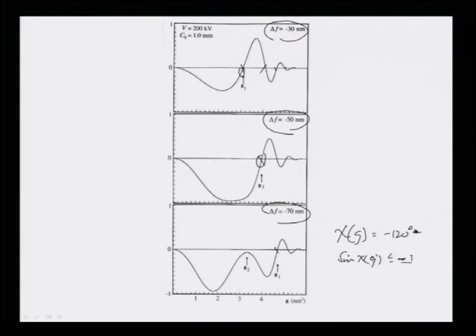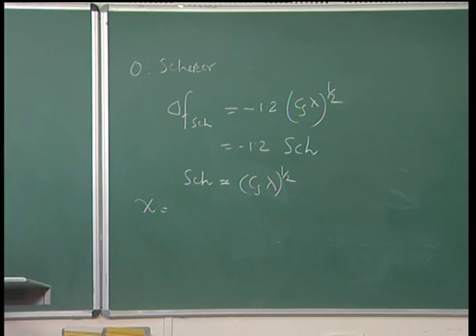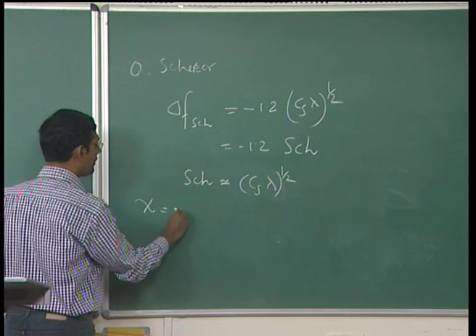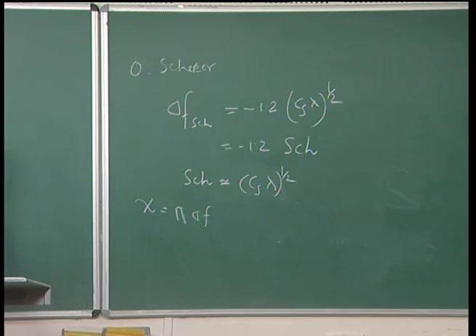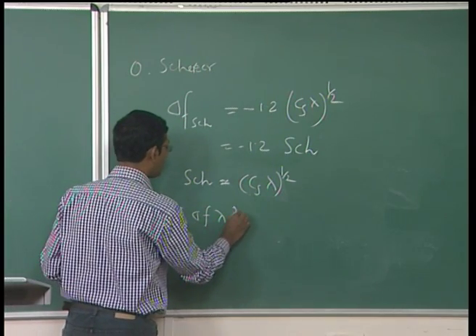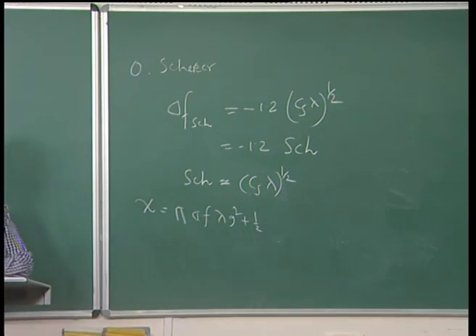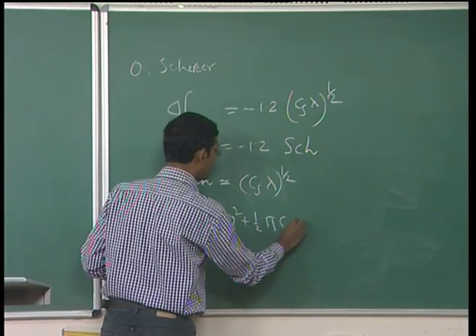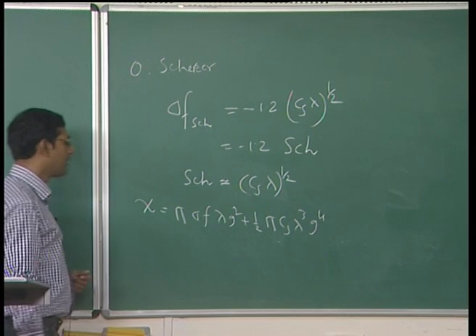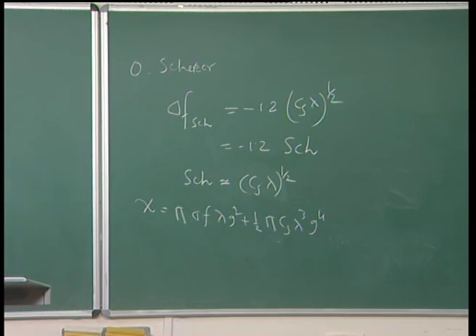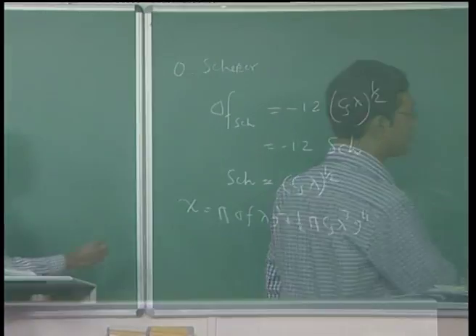Now, let us see how this can be derived using the formula which I have already given you for psi. For psi we have seen that it depends on the defocus and also the spherical aberration constant. So psi is equal to pi delta f g square lambda plus half of pi Cs lambda cube g to the power 4. So, if I minimize this function at a particular value of g, I can get basically the Scherzer focus. So, let us do that.